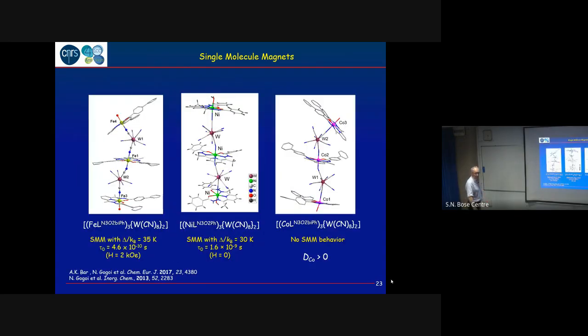So here the tungsten has spin one-half. So we have a ferromagnetic exchange between the two species here and here. And for the nickel, the exchange interaction is quite large. So in tungsten, there's no anisotropy. Anisotropy comes only from the seven-coordinated centers, nickel or iron. So here the second partner is just to link and to introduce exchange interaction between them.